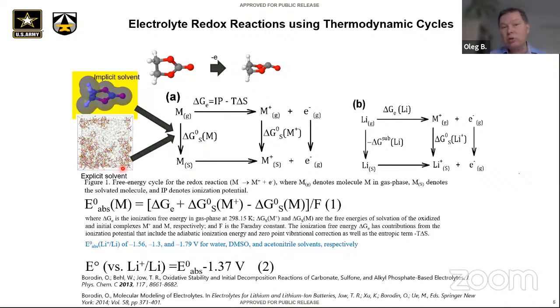Instead of doing explicit calculations, which are much more challenging, we are going to use implicit solvent calculation, in which the solute is surrounded by a polarized continuum with some dielectric constant, which makes a difference on both reduction and oxidation potentials. The typical drawback is that this model needs to be parameterized, and it's very sensitive to the radii of atoms which are used. On one hand, this model is the most accurate for organic solvents, but if you have lithium surrounded with something, then we include the solvation shell in order to explicitly consider it and use the implicit solvent model for the rest.